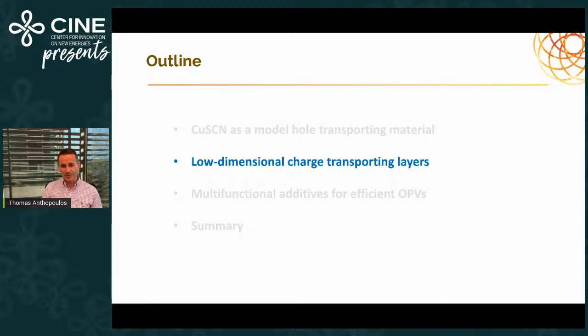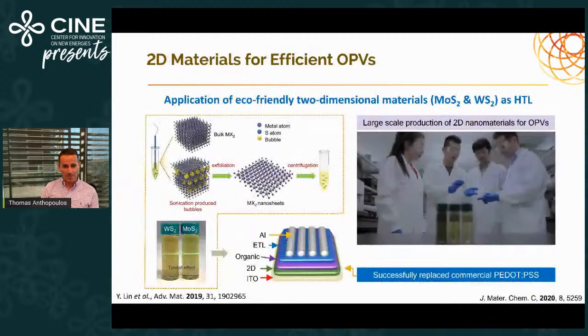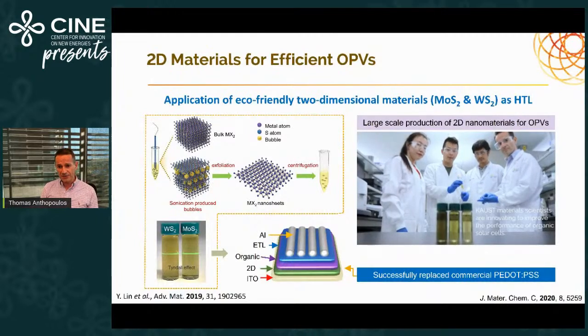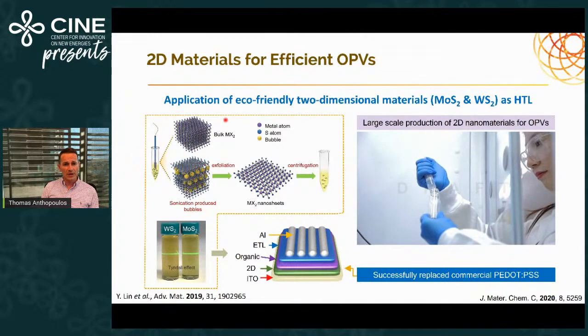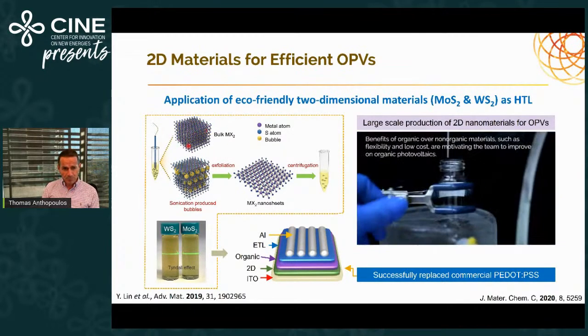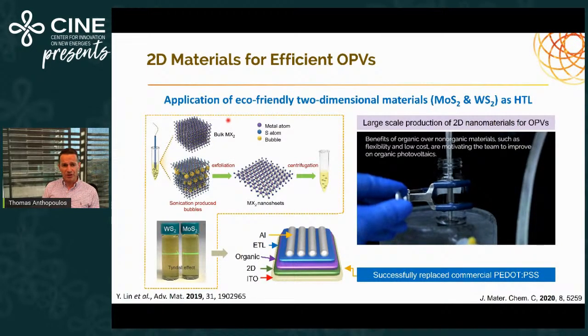presents numerous problems. So while we were working with the copper thiocyanate, we were also exploring simultaneously a number of other materials, and I will highlight a few families here. What I call low dimensional here is essentially materials which are very thin in terms of the layer thickness we're trying to form. One of these systems, and this little video we recorded when this paper was published in Advanced Materials, relates to the exfoliated two-dimensional chalcogenides such as molybdenum disulfide and tungsten disulfide. Essentially, these are two-dimensional, layered materials.